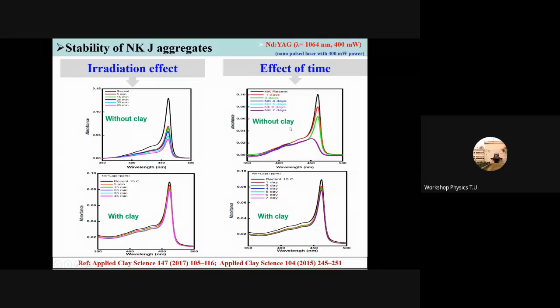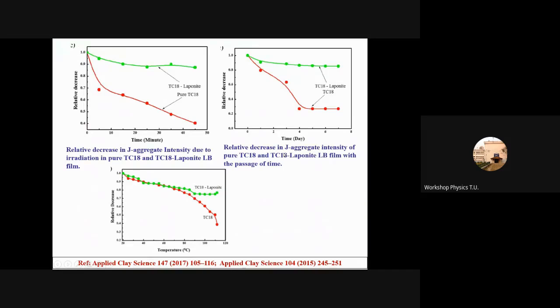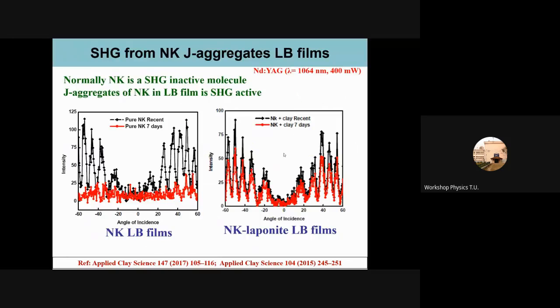So we demonstrated this. This is just J aggregate characteristics, so I am not explaining this. Okay, so here I am showing the SHG signal, second harmonic generation, in the absence of clay, the first one. The black line shows the SHG signal for recently prepared films. But after 7 days, you can see in red that the intensity decreases. This is because LB films of organic molecules are mechanically unstable over time.